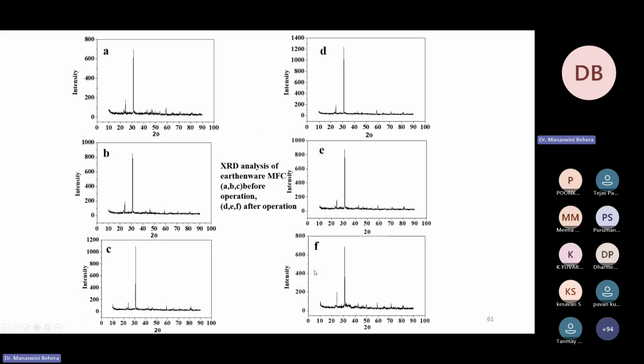So these are some of the XRD analysis. Many people ask what will happen to this earthen material after long-term use in a wastewater environment. So we carried out the XRD analysis. Figures A, B, C are before use and D, E, F are after use. And this is not a short-term operation. It is almost 2 years, 3 months of operation. We took a sample of the material and saw that there is no change in the composition and very little deposition, which can be manually cleaned. So it gave a better performance, and the longevity of that material is also established. It can be used in the long run for wastewater treatment.